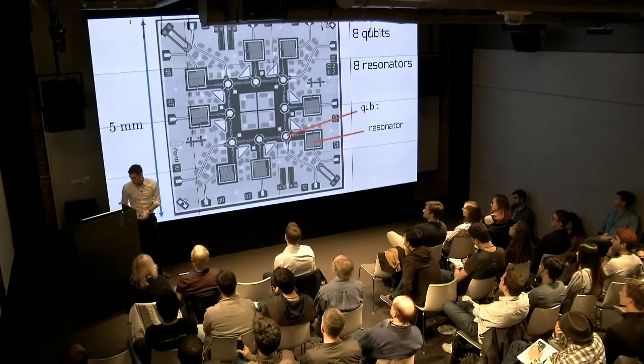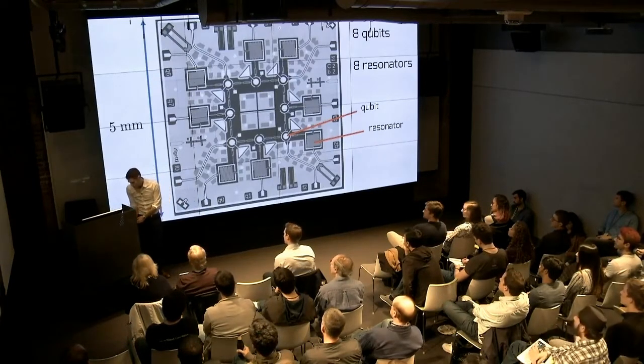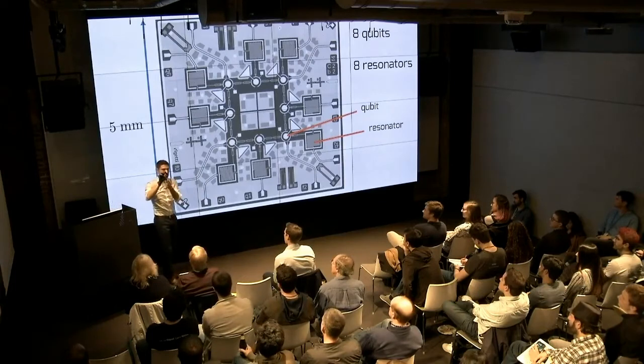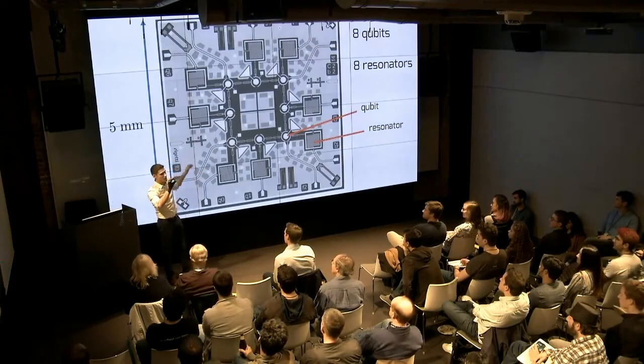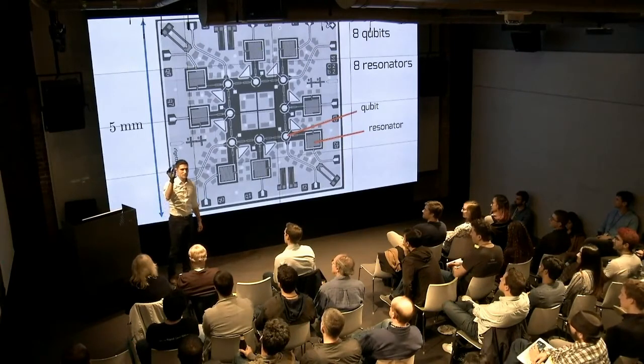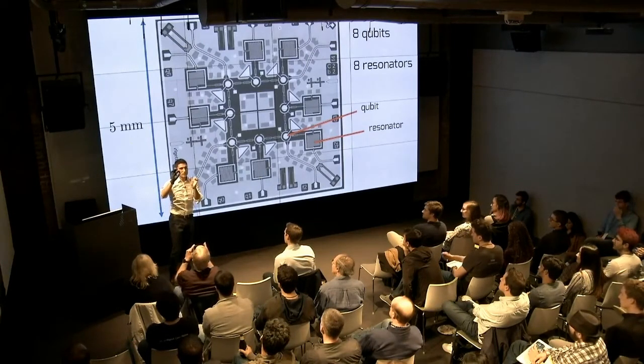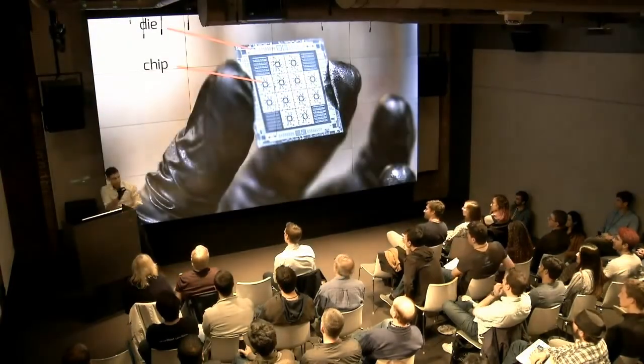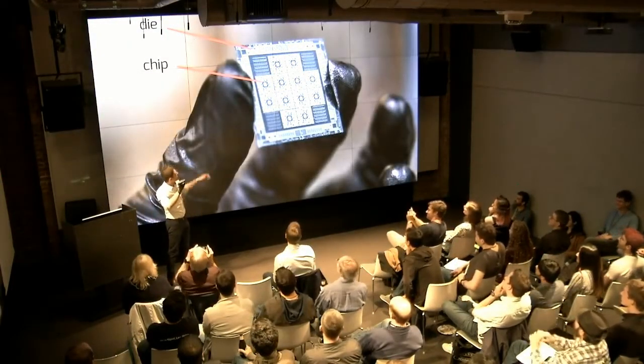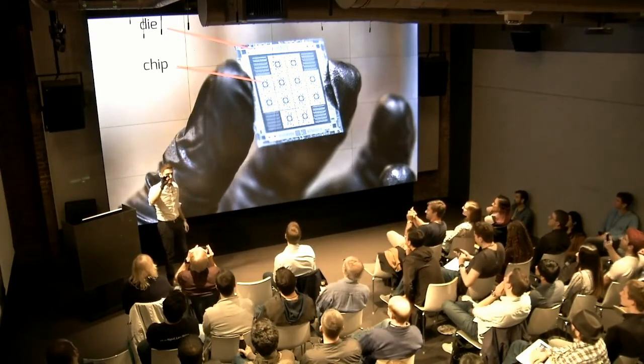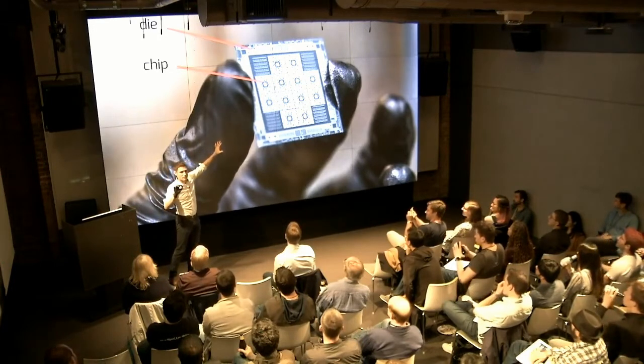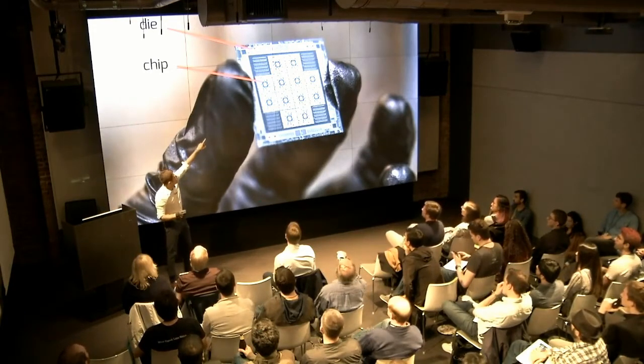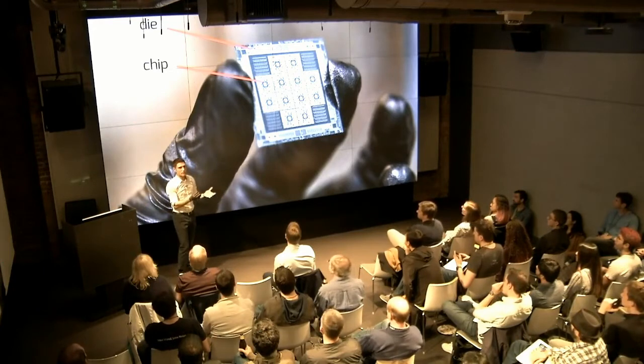I have a sample here I'd like to show you. This is a chip that was fabricated at Rigetti — this is an actual quantum computer. It's on silicon with aluminum on top, and the aluminum is just 100 nanometers thick. The die is 25 by 25 millimeters, and here you can see 12 copies of the same chip. What we do at Rigetti is cut the chip with a saw or blade, take just one little square, measure it, and use it as a quantum computer.